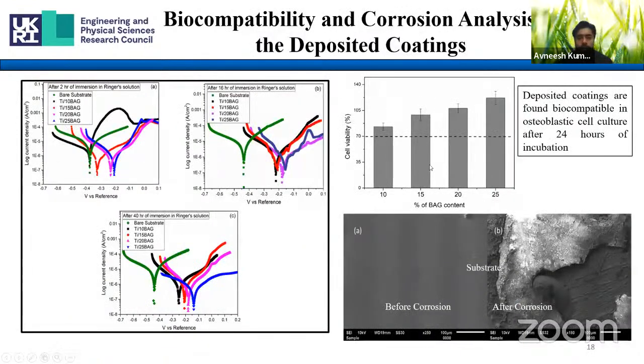Then we have done some biocompatibility analysis. For that, we put our already deposited coatings into an osteoblastic cell culture for 24 hours and monitored the cell viability. Cell viability is nothing but the live cells. The threshold value was 70%, and we were able to achieve more than 70% cell viability, which says that all the coatings were biocompatible.